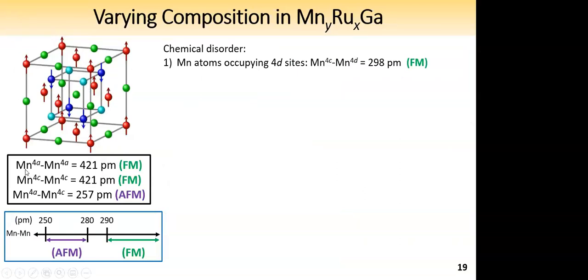Below the unit cell, I'm giving all of the distances between the different manganese atoms. And on the very bottom, I'm showing a scale of distances where between 280 and 250 picometers, we can get antiferromagnetic coupling, and anything above 290 picometers leads to ferromagnetic coupling. So this corresponds to what we find from the distance analysis.